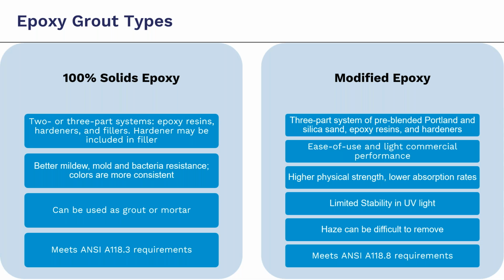It has limited stability with UV lighting, so you may experience color fading, and that's what the limited is. Haze on a modified epoxy can be difficult to remove. As you are cleaning up after you install the grout, you may get some grout haze on the tiles. It can be difficult to remove if you have a modified epoxy versus 100% epoxy or a cementitious grout. And this does meet the 118.8 requirements we talked about earlier.